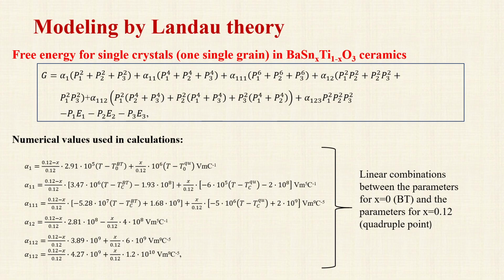The most facile way to describe phase transitions in barium titanate-based ceramics is to employ Landau theory. We use the sixth order expansion of the free energy in which alpha parameters are dependent on temperature and substitution degree x. In fact, alpha parameters were calculated as linear combinations between the parameters for pure barium titanate, very well studied in literature, and parameters corresponding to x equal 0.12, for which a quadruple point was reported in tin-doped barium titanate ceramics at 40 degrees Celsius.